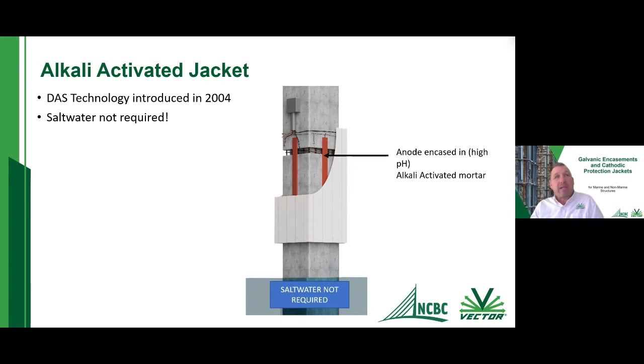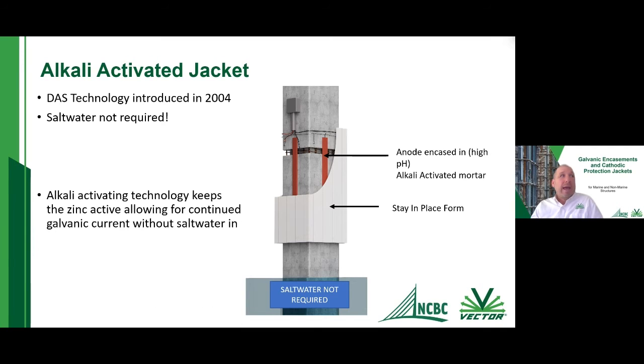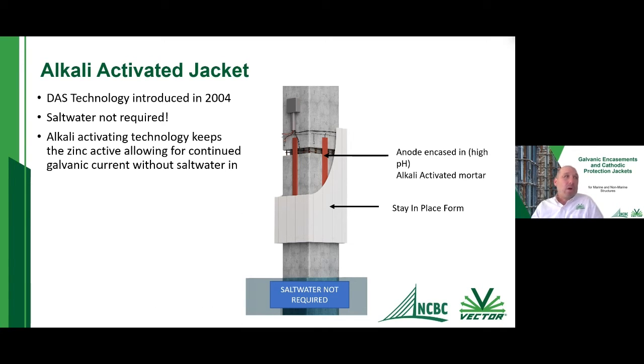So we're doing the exact same thing here. We're just basically embedding the zinc in a really, really high pH mortar. And we're going to use the same stay in place form as well. That high alkaline mortar keeps the zinc actively corroding, and we do not need salt water for it. So this is an area where if you're looking to protect something higher up, you can install this type of activated jacket higher up, outside of those elevations where you don't have access to the salt water.